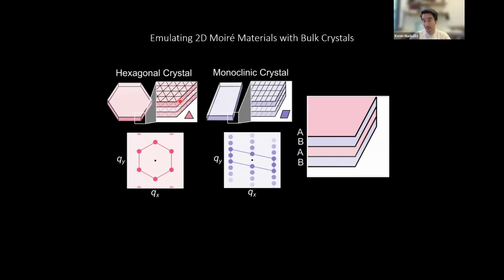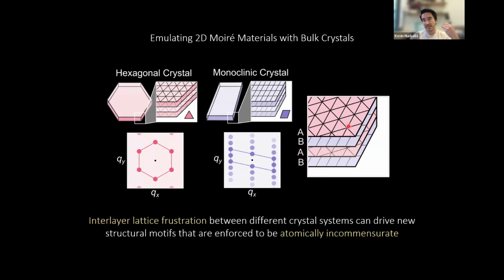And so I can't do this atomically commensurately. But in some situations, there are accommodative reaction products that can satisfy a partial subset of the allowed symmetry constraints. So here's one that the misfit layered compounds in the literature took. If you align the rightmost Bragg planes of this hexagonal lattice with the rightmost Bragg planes of this monoclinic lattice so that they're atomically commensurate in one of the two in-plane lattice directions, I'll effectively satisfy half of the symmetry constraints of these crystals, but in doing so, the system will necessarily be aperiodic in the orthogonal direction.